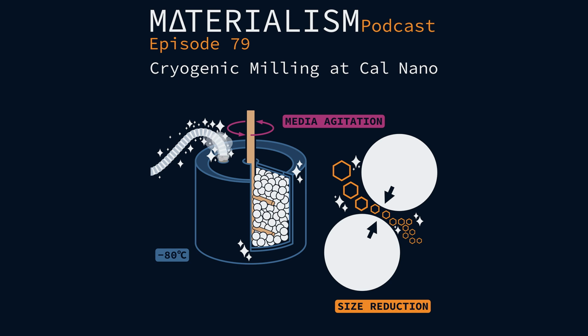There's ultrasonic versions of this. Now, it's typically going to be fluid-based, and so now you introduce ideas like which is your solvent, what your flow rate looks like. There's still a lot of tunable parameters there, but in general, the scales, because you can have a big reservoir of your slurry, and then it can be passed through the region where the actual ball mills are kept and where the particle size reduction is taking place. Yeah, and you can jacket it, so you can keep it cool as you're scaling too, so that's a big thing if you want to keep heat down in the process.